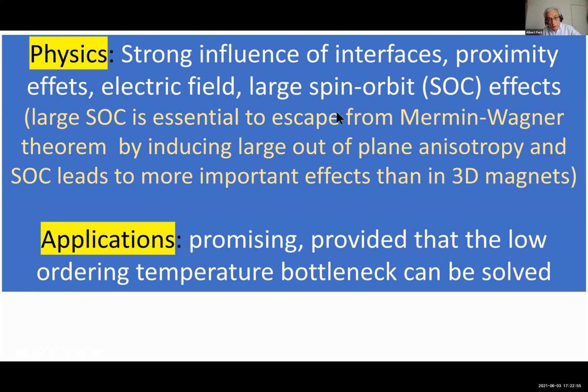So because all these compounds escape from this theorem, most of them have large spin orbit effects, and you can exploit these spin orbit effects. And so there are many interesting properties related to the spin orbit coupling. For the applications, of course, we'll see that they are promising, provided that the low ordering temperature bottleneck can be solved. And we see some examples of ordering temperature higher than room temperature.